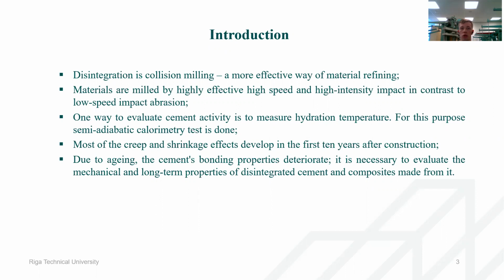The way that we use to assess the disintegration effect to the activity regeneration of the cement was the semi-adiabatic test, or in other words, we measured the hydration temperatures of cement mortars that were setting, and long-term property assessment was done, basically assessing the shrinkage and creep strength of the cement mortars.